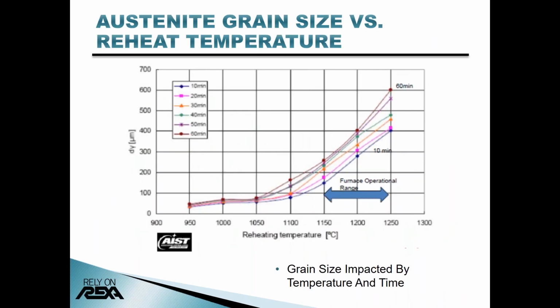In this figure, the austenite grain size and reheat temperature is plotted with various soak times ranging from 10 to 60 minutes. It is important to note that in the target operating range of 1050 C, it is not flat, but the grain size will increase with longer times and higher temperatures.